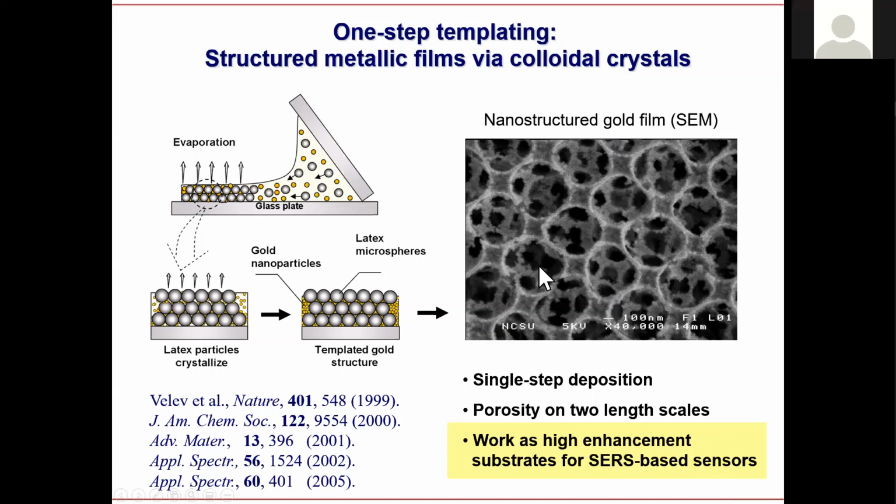And how thick is this then? I see 100 nanometers. How thick is this layer now? No, this is 100. So this is 100 nanometers here. See, this is this bar. The bar here is 100 nanometers. So these are 20 nanometer gold nanoparticles. And the thickness of the layer in this case is, I think, probably about half a micron or something like that. This is 1 micron particles here. You can see 100 nanometers, maybe even less than a micron, right? So 1 micron from here to here, half a micron down, because this is less than a monolayer.